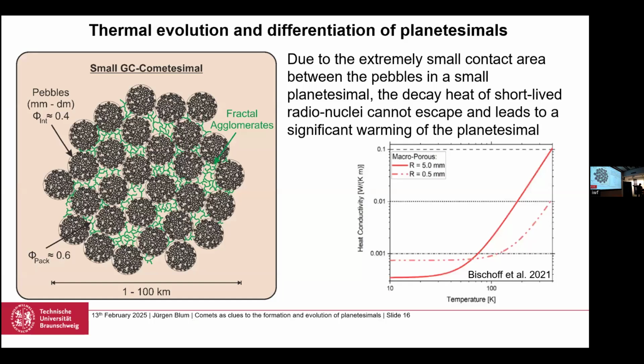Okay, again, so this is our view of a planetesimal, so as a pebble pile. And here are our two models for two different radii of the pebble. So this is a millimeter pebble, this is a centimeter pebble. And we have a model of how the heat conductivity goes as a function of temperature for those two pebble piles. And if you're familiar with heat conductivity, typical materials have on the order of unity in watt per Kelvin and meter. So 1 to 10 watt per Kelvin and meter is the normal material. Here we're dealing with less than 10 to minus 3. So really nothing. So much worse than air. So air is here.